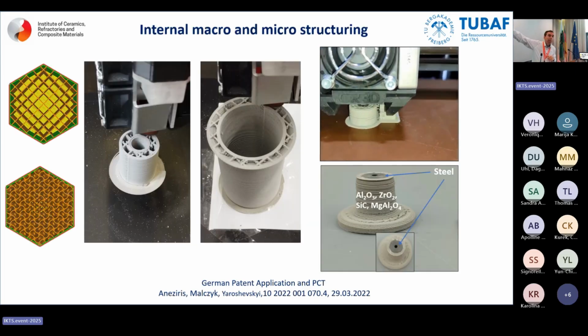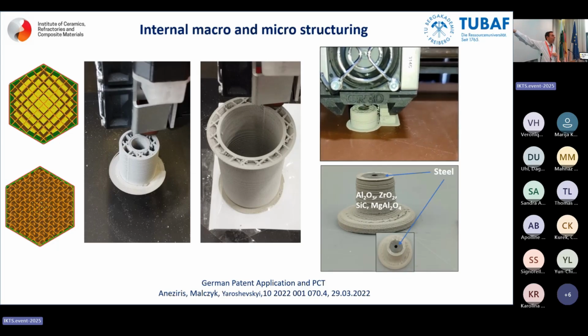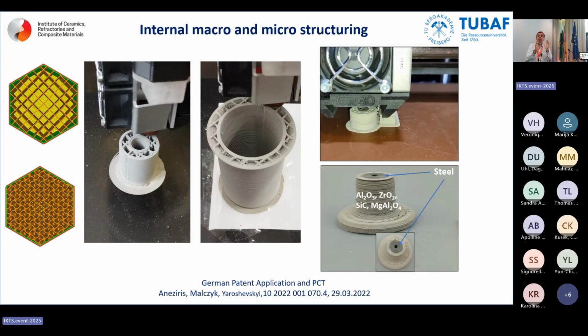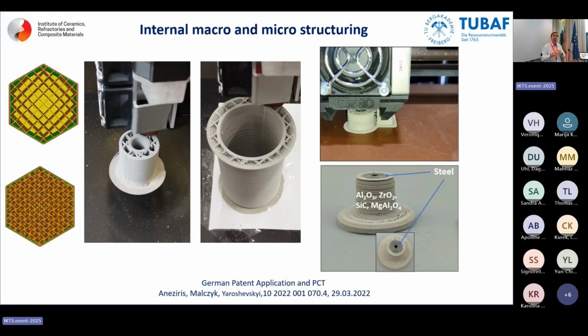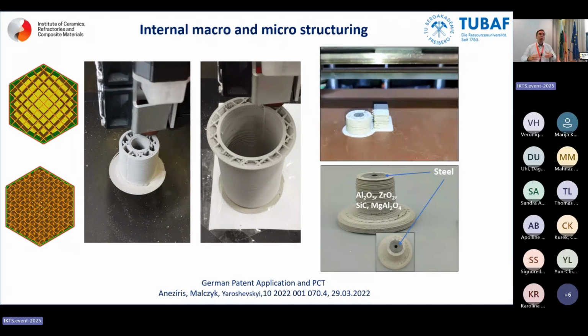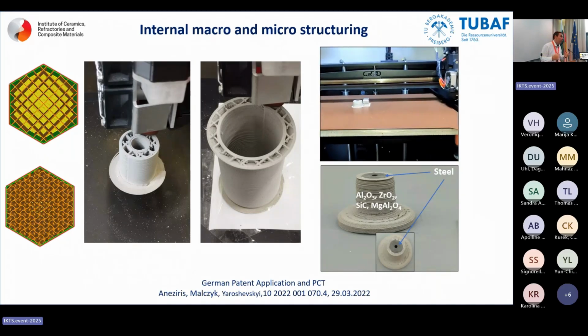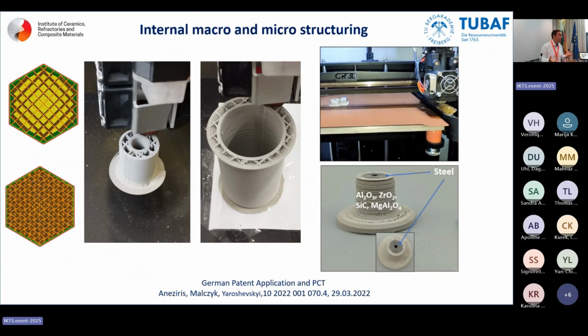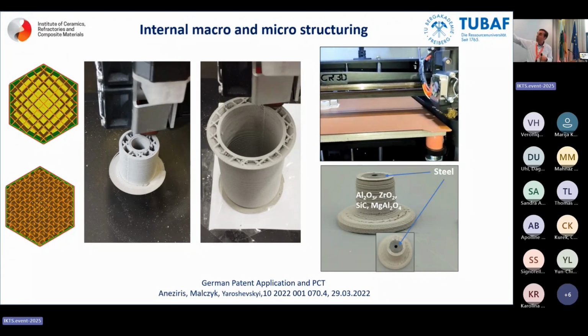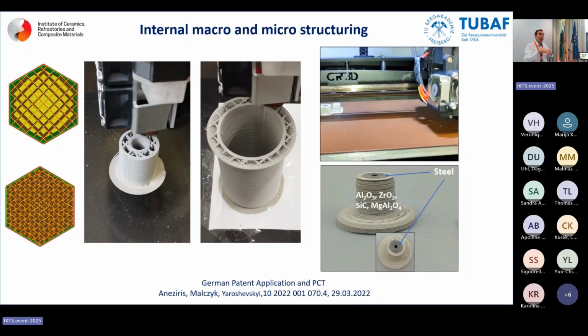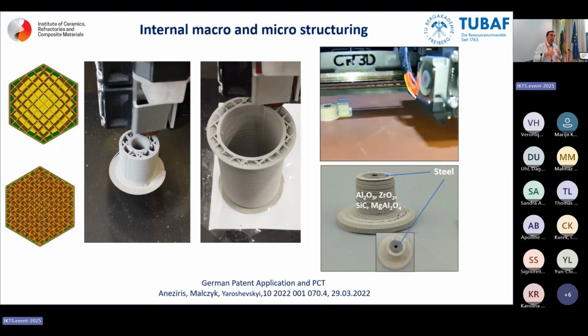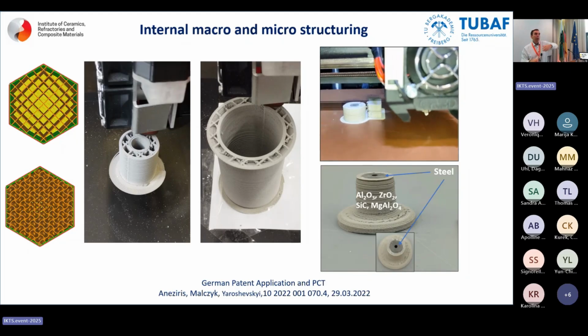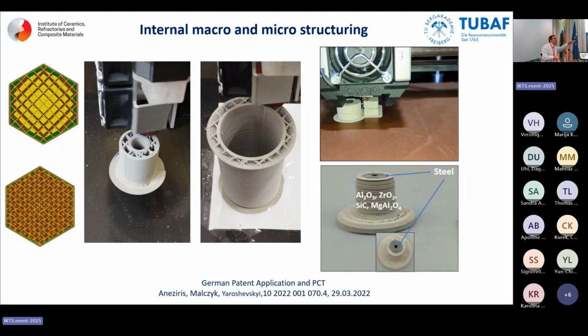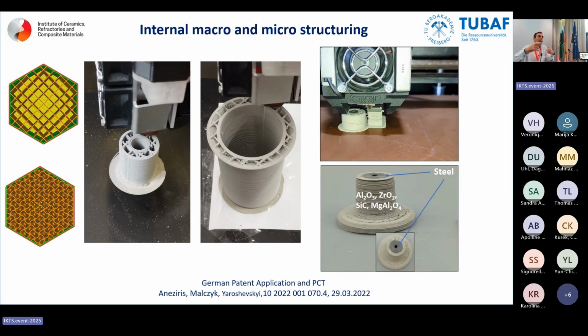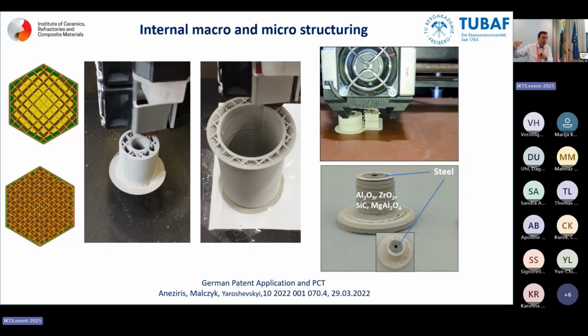Yes, we want to make macro pores, macro channels, where I have to be tight, high density, corrosion, erosion resistance, yes, but the structure behind, it could be not so dense, in order to be able to withstand the thermal shocks. No? Play with materials. We see you can make steel inside if you want to fix it with an anchor, and outside makes a ceramic. And of course, as John mentioned, you will have a distribution, yes, of the phases, which as a gradient structure could withstand thermal shocks.